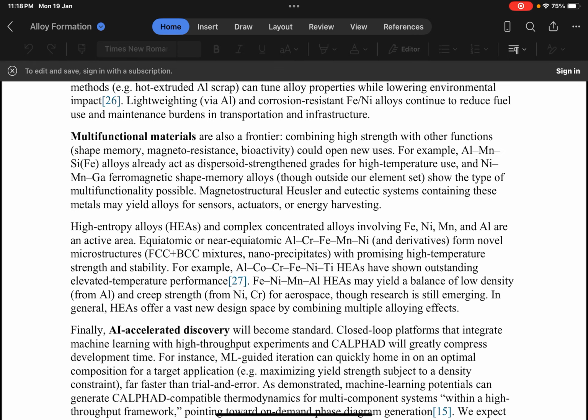High entropy alloys and complex concentrated alloys involving iron, nickel, manganese, and aluminium are an active area. Equiatomic or near equiatomic aluminium, chromium, iron, manganese, nickel, and derivatives form novel microstructures with promising high temperature strength and stability. For example, aluminium, cobalt, chromium, iron, nickel, titanium high entropy alloys have shown outstanding elevated temperature performance. Iron, nickel, manganese, aluminium high entropy alloys may yield a balance of low density from aluminium and creep strength from nickel and chromium for aerospace. Although research is still emerging, in general, high entropy alloys offer a vast new design space by combining multiple alloying effects.